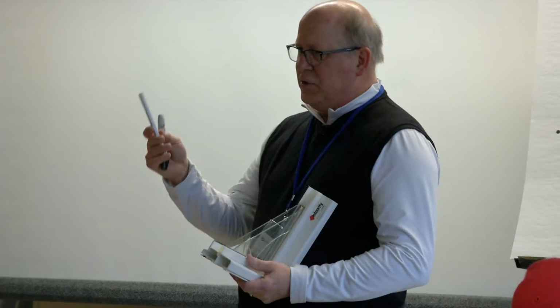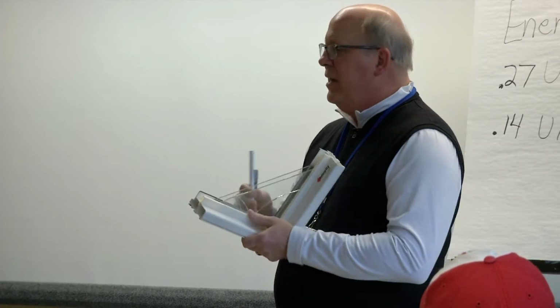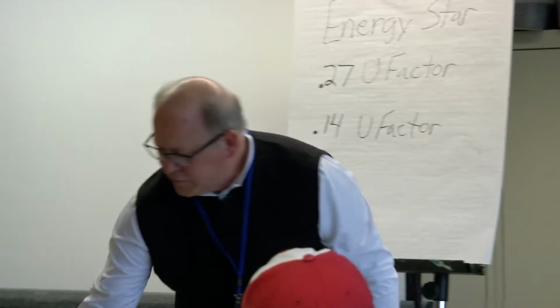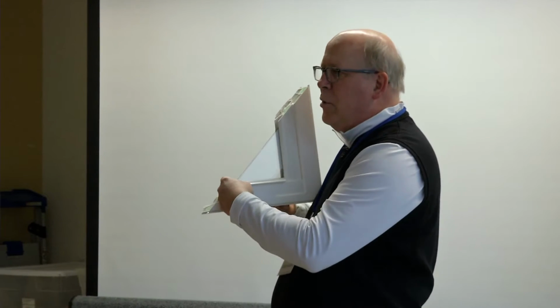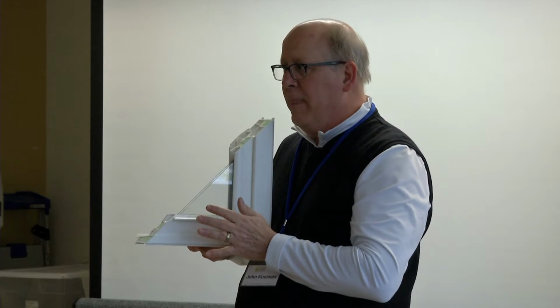These metal spacers too don't expand and contract, but they don't always come back to the same place and shape, and seals start breaking on them. My favorite spacer in a window is the one that's on this Soft-Lite window. It's called Super Spacer. It's a thermoset silicone polymer. In other words, thermoset means it has memory and it always comes back to its shape. And the silicone is almost the same expansion and contraction rate as glass, so it moves perfectly with the glass.